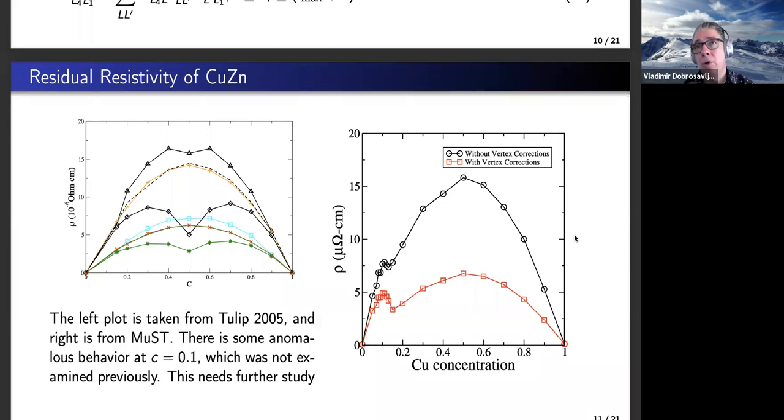Whereas when the conductivity drops to 0 and there is a phase transition, that is not affecting the average density of states, it's affecting only the conductivity. And so what they show is that there is a subclass of vertex corrections which do the task, right? The Green's function doesn't do it, the effective medium doesn't do it, it is the vertex correction. So it's not cluster CPA that does that.